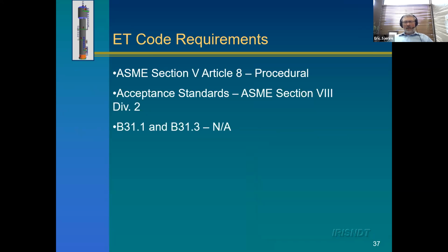Now, the codes are a little simpler, so we don't use this so much in our industry. Article 8 deals with eddy current, but it just doesn't have the detail that the other articles have because it's not a common technique that we see in our industry. And we don't have acceptance criteria in ASME Section 8 because we never use it for new fabrication. It's always used for in-service inspection. So the code requirements for eddy current are a lot less detailed than the other techniques just because it's not used as much. And the main reason it's not used is because we can't penetrate thickness well.